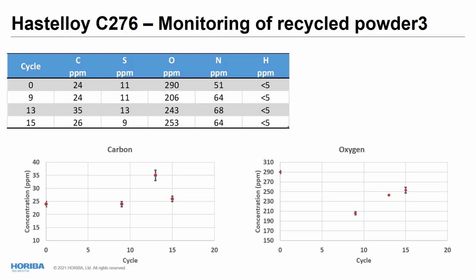If you look at oxygen, it's a little bit different. And the closer look shows a high concentration on the initial powder at 290 ppm. And then after, all the analyses were lower than this initial concentration, but with a steady increase. From cycle 9 to 15, we are ranging from 200 to 250 ppm. That is a significant difference.